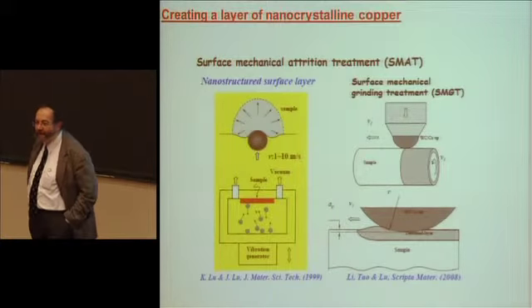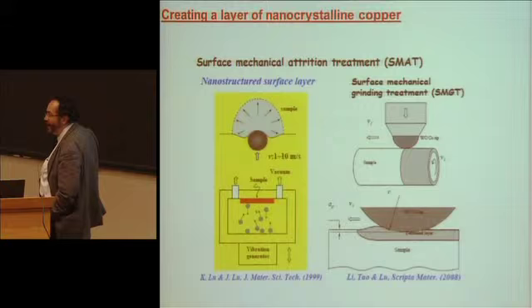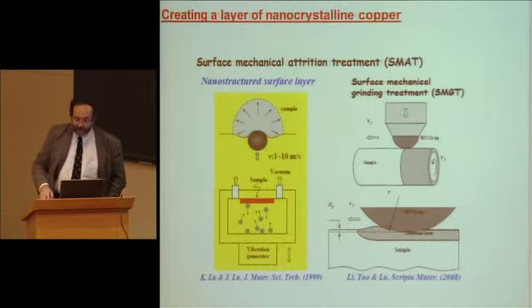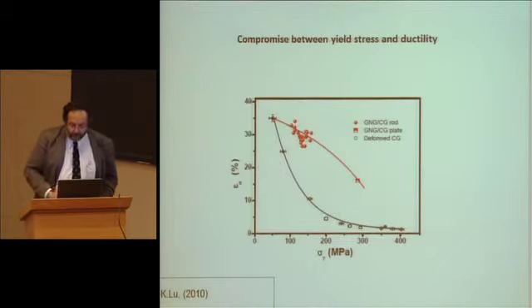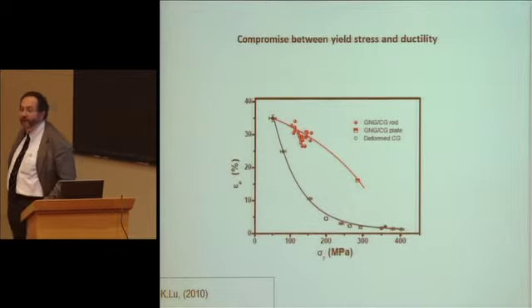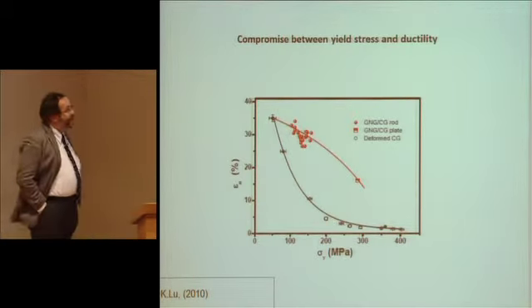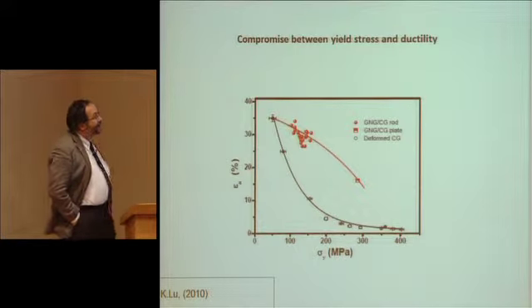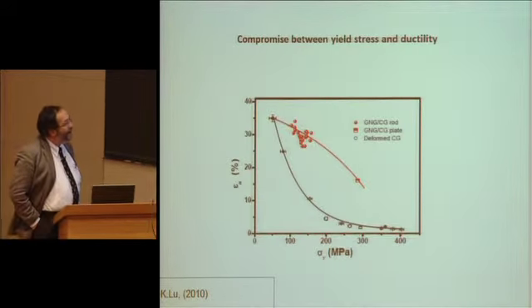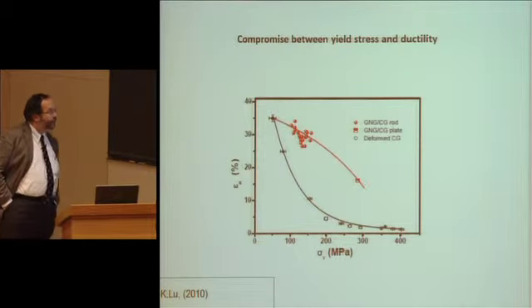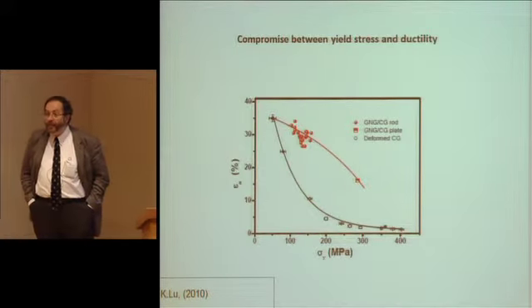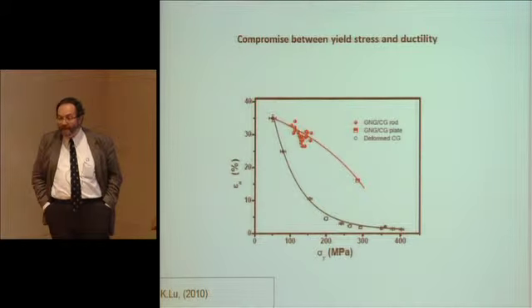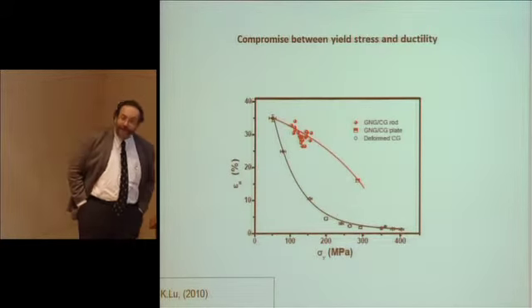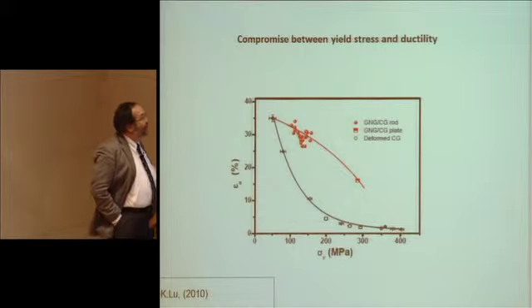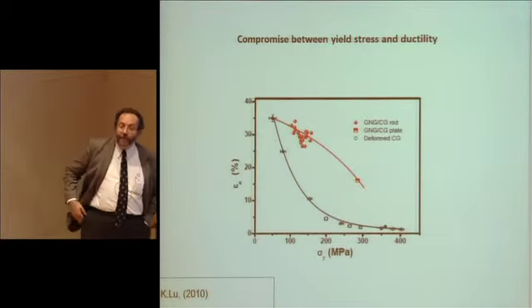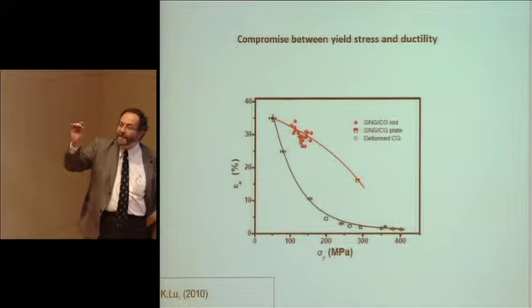It's a surface treatment that's quite brutal, not necessarily at room temperature. And you can have a copper part, for instance, a lot of deformation, overblasted, where you have high elasticity limit and high ductility. Here in black, you have the classic curve, the classic graph of work-hardened copper. The more it's work-hardened, the less deformable it is. Again, the engineer's nightmare.